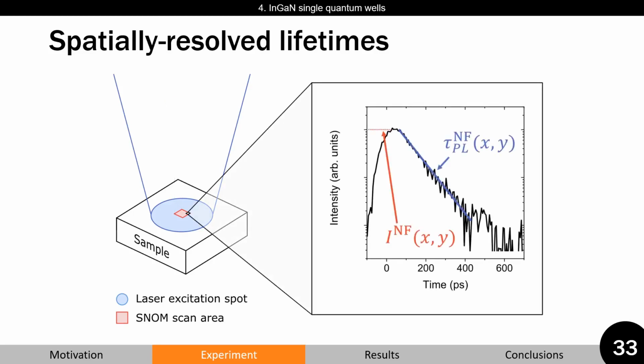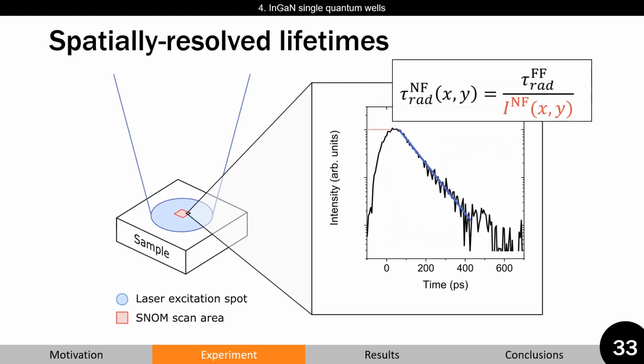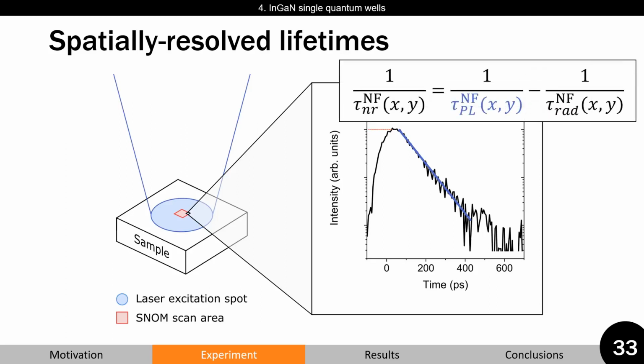Therefore, in addition, we can resolve photoluminescence transients with 100 nanometers spatial resolution. Then, by calculating local amplitudes and local lifetimes, we use an assumption that variations in amplitude in our studied low defect samples are due to variations of internal quantum efficiency. Then, by using our spatially averaged radiative lifetime measured in the far field and local variations of amplitude, local radiative lifetimes can be evaluated. Knowing radiative lifetimes and photoluminescence lifetimes allows us to spatially map non-radiative lifetimes.